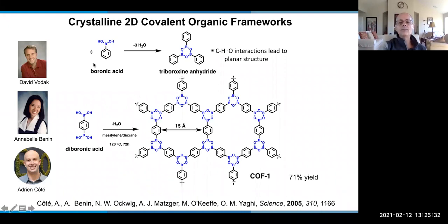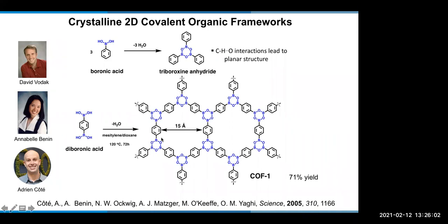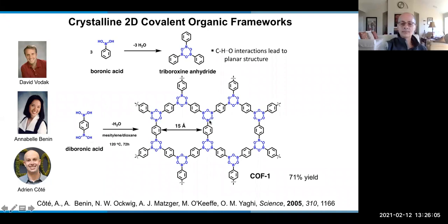And this is where we had our success back in the early 2000s. We looked at boronic acid, and it was known that boronic acid trimerizes to make this triboroxine anhydride. And because of a CH-O interaction here, this molecule, if you look at its crystal structure, is a planar molecule. So then our thinking was that since that's a planar molecule, I could try a diboronic acid. And in doing so, if I can succeed in crystallizing the dehydrated structure, then I would have made a graphitic type of